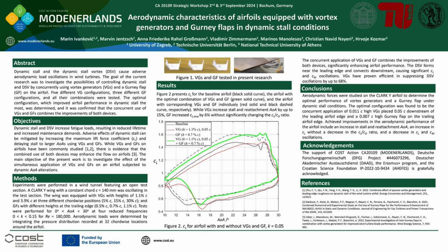Optimal performance of the airfoil was achieved when a 0.7% chord height Gurney flap was combined with 1.1% of chord high vortex generators at 5% of chord from the leading edge. While Gurney flaps produced an increase in CL max of 6%, without a significant increase in glide ratio.